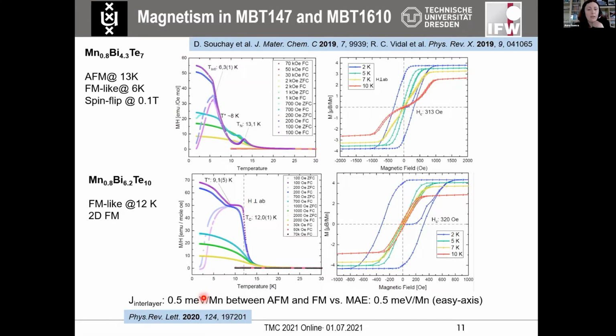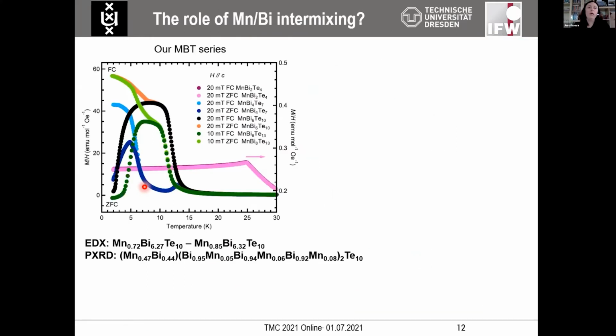So in this paper, our collaborators developed a very nice explanation for this fact. They said that in fact, this metamagnetic transition, this antiferro versus ferromagnetic ordering, is an interplay between the exchange coupling that is being subsequently reduced as we dilute the phase with more bismuth telluride, and the uniaxial anisotropy. Also in the series of our MBT samples, so here we have the whole family from 1-2-4 to 1-8-13, that seems to be very nicely followed. So you can see that the phases are getting more ferromagnetic-like as one moves towards 1-8-13.